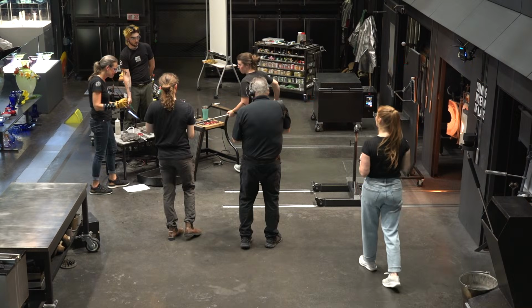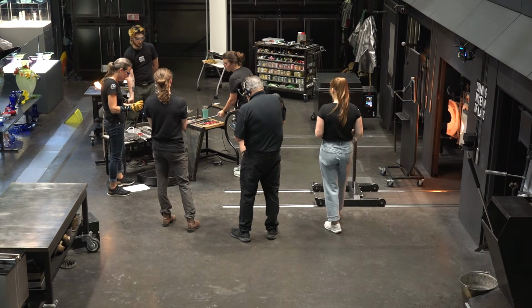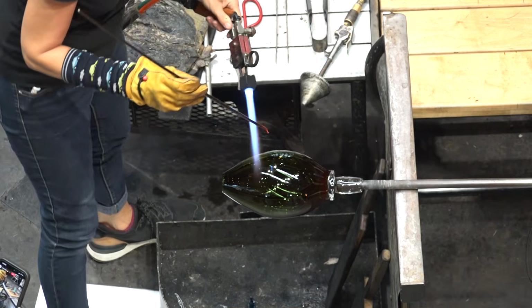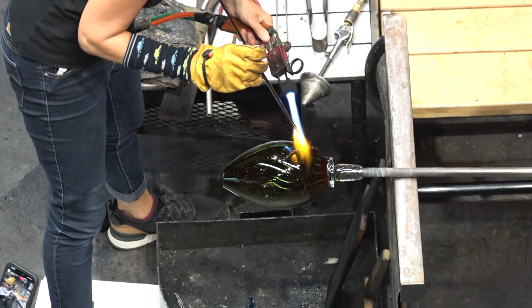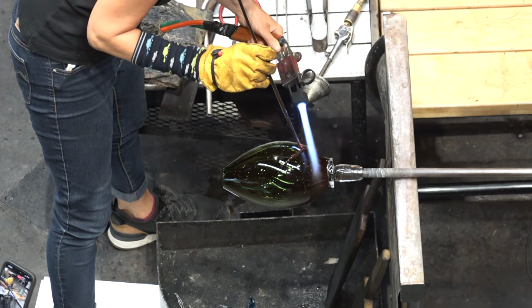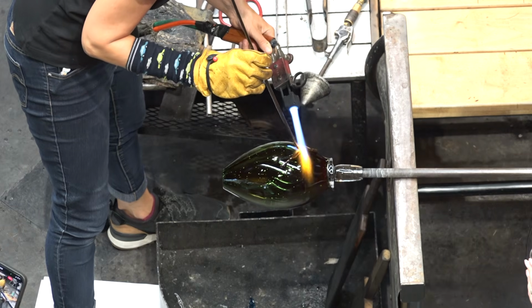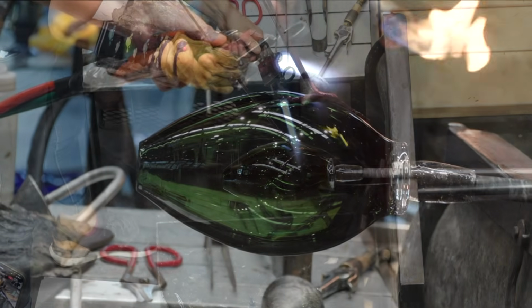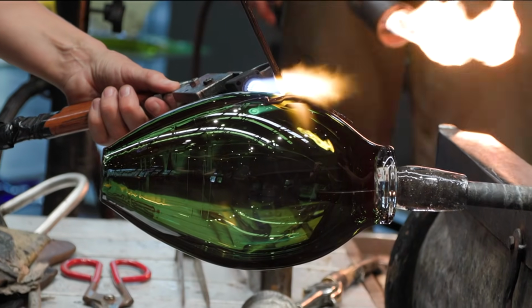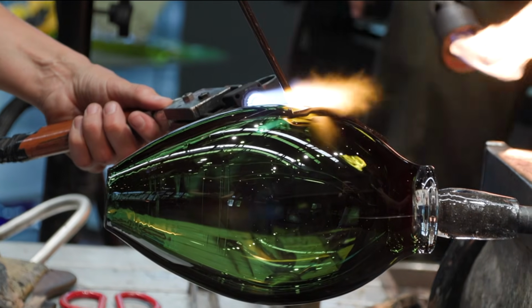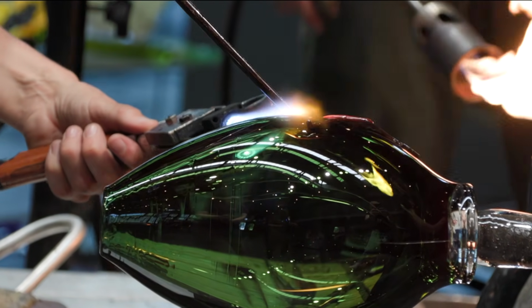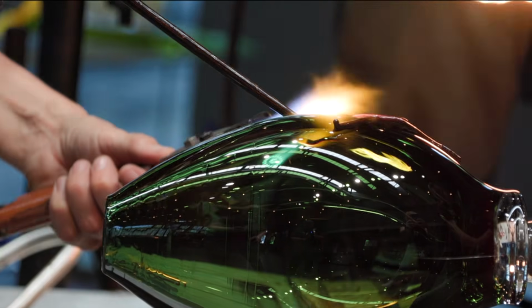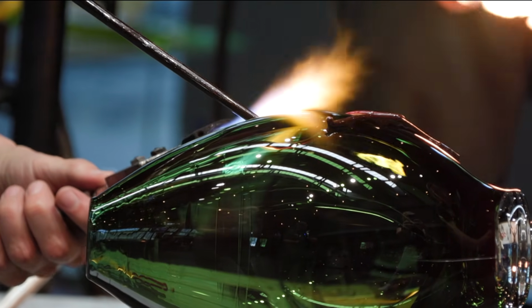So she'll heat up the rod as Katie takes the glass for a quick flash. We never stay out of the oven for too long. If you stay out of the oven for too long, the outside will cool faster than the inside, and it will build up stress in the glass. Stress in the glass will eventually lead to a crack or a break. So you're going to see them maintaining temperatures of over 1,000 degrees the whole time we're working.